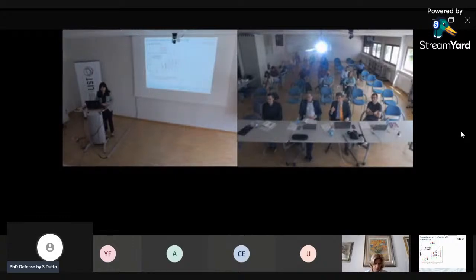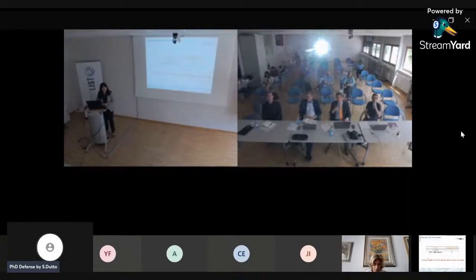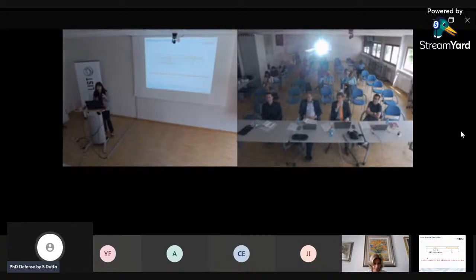For some of these, you find, I think it was later on, a polarization of something like 50 microcoulombs, right? This is in the really big supercell. Does it depend on the size of the supercell? Do you get something similar for the small one, in the same order, in silicon? I calculated with the smaller cells, for example at 25%, and I get around 46 microcoulombs.